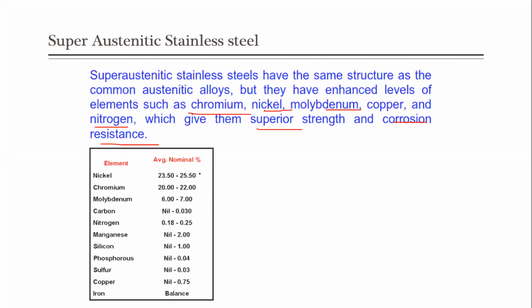Nickel will be added around 23 to 25%, whereas in conventional 316 ASS, the nickel is limited to 10%, whereas in super austenitic stainless steel, the nickel content will be around 23 to 25%. And the chromium content also is enhanced, whereas in commonly used 316 alloy, you will have around 18% of chromium. Here you will have 22% of chromium. And the molybdenum also is increased in super austenitic stainless steel. Here you are adding around 6 to 7% of molybdenum, whereas in conventional 316 alloy, it will be around 3 to 4% of molybdenum present.